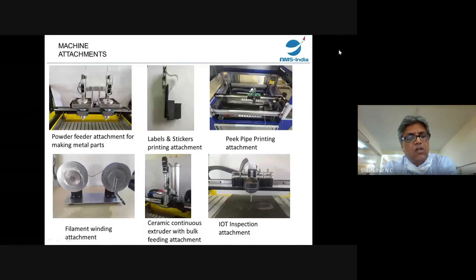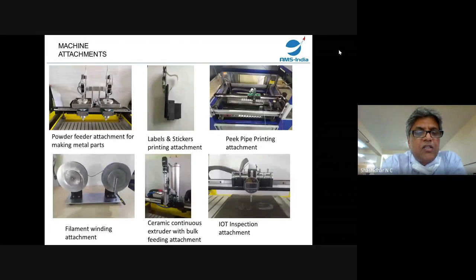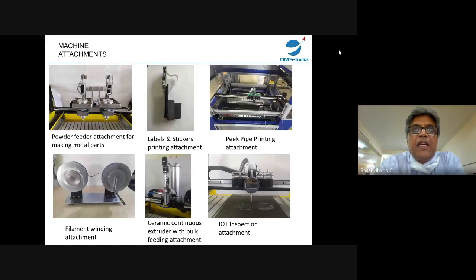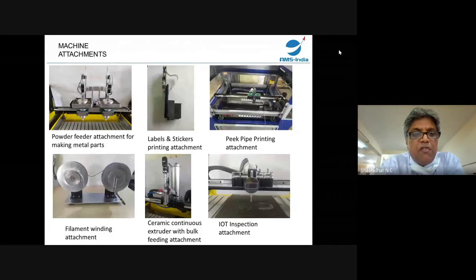The other attachments that go with the machine: we have a powder feeder attachment, so we can actually print powders. You can print sand and you can print iron powder. And when you print sand and iron powder in different layers, the iron powder is what actually takes the shape of the end part that we need. Then we have an infill material kept on top in the crucible, and then we put it in our furnace, and thereby the infill will melt at a lower temperature than the bare iron powder, and then it percolates down, diffuses, and makes a solid part. This is a patented design of ours. It is called the micro diffusion process. The powder feeder attachment is capable of doing micro diffusion, so making steel parts with that.